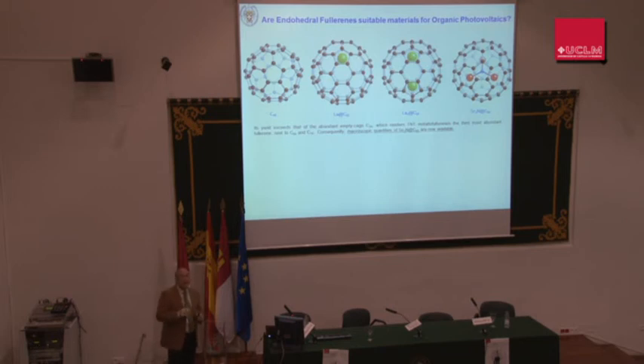I have had some discussion with referees when you submit a paper with this, and sometimes a non-expert referee on this material says in his or her comments, another example with fullerene, and you complain eagerly, because that means that this referee knows nothing about this material. For instance, scandium nitride should be considered something like this. Scandium nitride means that you have 6 positive charges in this complex. Actually, scandium nitride does not exist alone, because you need another 6 negative charges, so you need a counter ion. And in this particular case, these negative charges are spread on the fullerene surface. So these are really new materials, and a fullerene having 6 electrons on the surface, for sure the chemical properties and chemical reactivity should be different. So these are different species.